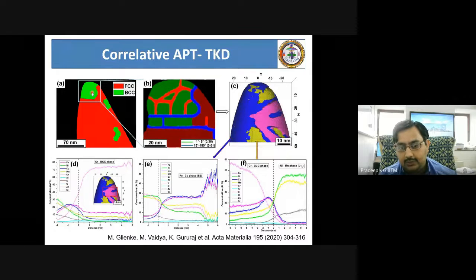So different types of precipitates of BCC nature, which is chromium rich, which is B2 iron cobalt rich, all of these things sitting on the same three-dimensional volume can be nicely identified with their crystallographic orientation, their crystallographic structure, and then as well as with their chemistry of these precipitates.